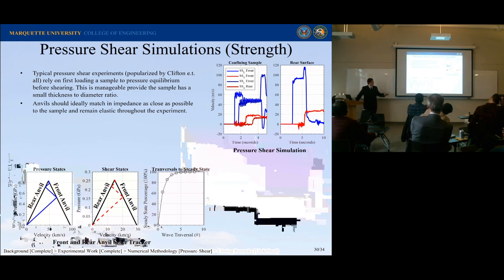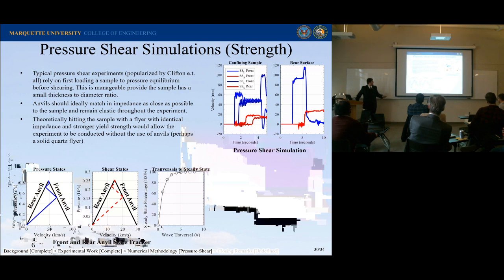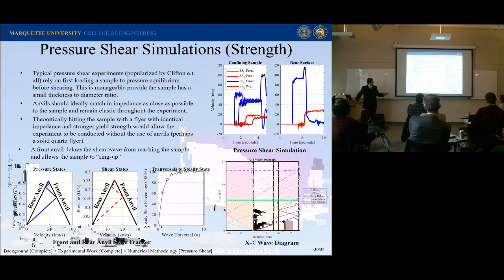And you can see on this back surface we have the hydrostatic, we come to a steady state, and then we can measure this shear coming off of the back. Theoretically we could hit the sample with an identical impedance and then we would get immediate pressure state, but we need something that's a higher strength than the material we want to study. Because if our anvils yield, then we're measuring the yield of the anvils and the material, and it's really hard to parse them apart. So you want anvils that are higher strength than the samples that we're trying to measure. So it gives us a whole bunch of constraints for our experiments.